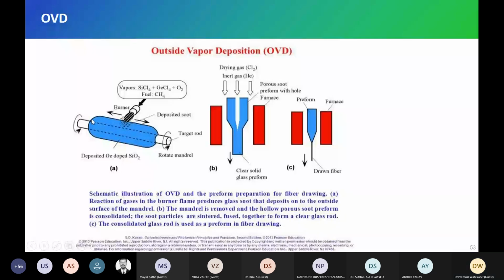So that's the first stage. Then we put this into the furnace. Okay, in the furnace, we increase the temperature to, suppose, 1500 degrees Celsius, and now the soot gets converted into glass. So we get the clear glass rod from the soot. Then again we take that glass rod and deposit SiO2. Again we get a similar structure. In the furnace, you get the clear glass, and then we can put it in the drawing tower and draw the fiber. So it's a complex structure.